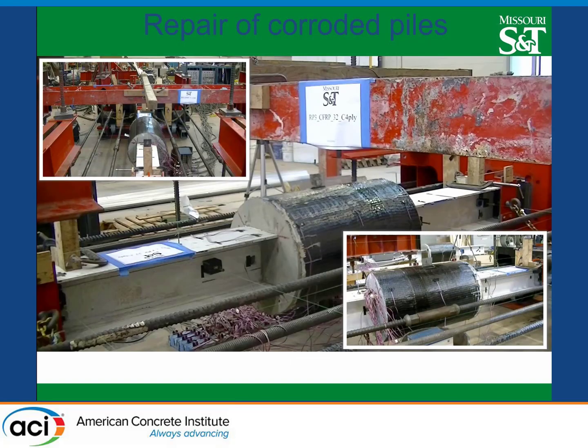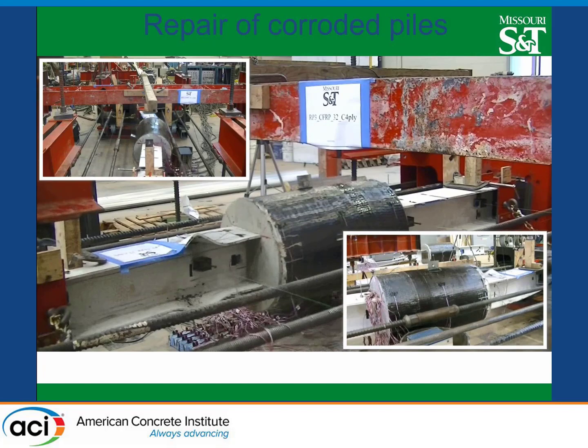Once we were done with this, we went and repeated the same test. Now, if you see over here, we moved the section. Inside the pile you have a severely corroded section. In fact, this pile was originally tested as a reference specimen, and after this we just straightened up the pile with all the residual stress on it, and it was still capable, with the wrap, of recovering the capacity of the pile, with the rupture occurring in a different section over here.